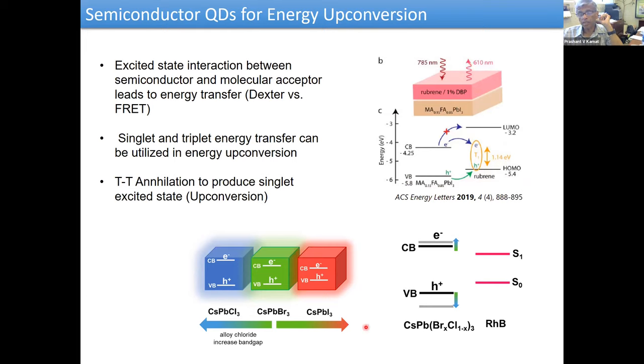from this process. Another interesting fact is alloying these halides. So this is cesium lead bromide, typically green fluorescent, this is chloride, blue, and iodide, red. But you can mix these halides, bromide iodide or iodide chloride bromide, and you can tune the entire region and you can change the band gap.